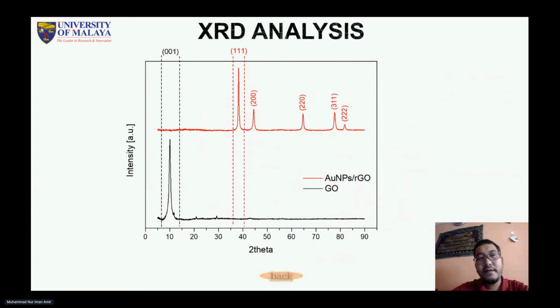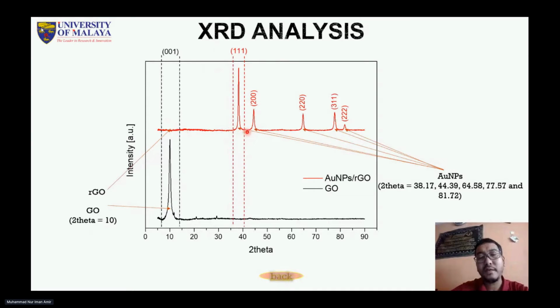Based on the XRD analysis between the catalyst used for the reaction and graphene oxide, what we already analyzed here is that there is no diffraction peak of GO observed in the catalyst sample. This is due to the transformation of graphene oxide into reduced graphene oxide during the synthesis that undergoes the reduction process, while the gold nanoparticle diffraction peaks with standard Bragg reflection, we already observed here.